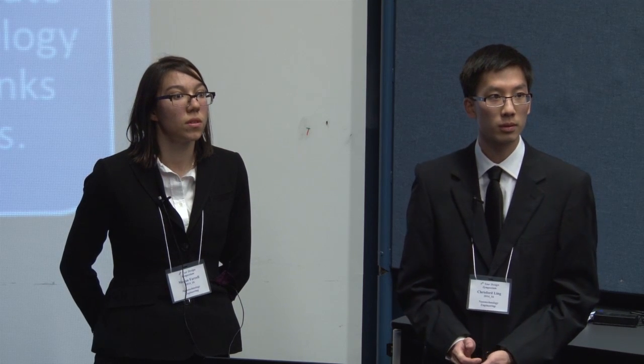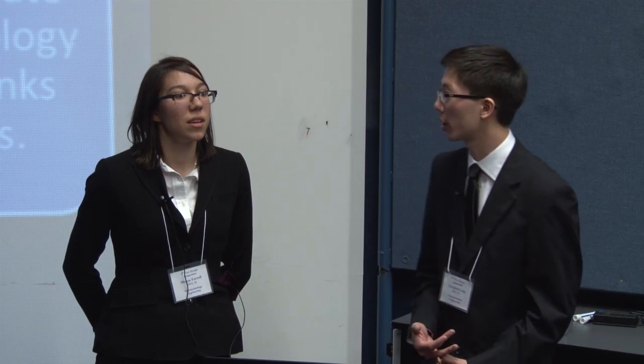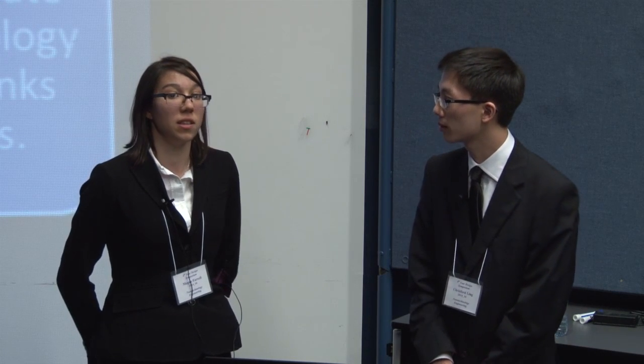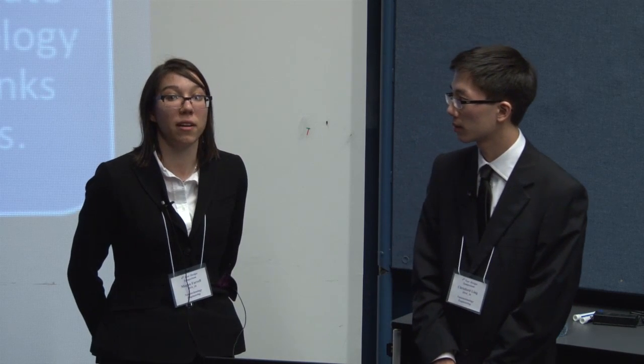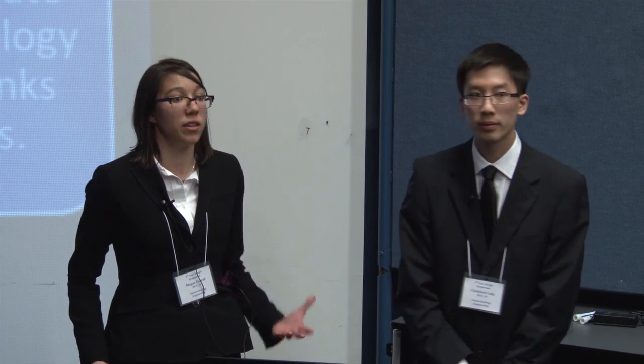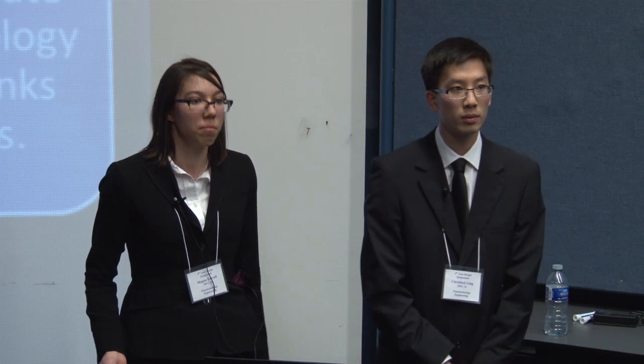But you know that theoretically graphene should have the highest, right? Yes. I don't think graphene is used extensively in lithium-ion cells of high capacity because while it has high surface area, structuring it into batteries is more of a problem. Again, it's very thin, right? I think the general material used, especially in vehicular applications, is graphitic. So not single film graphene, but rather thicker multi-layer pieces.